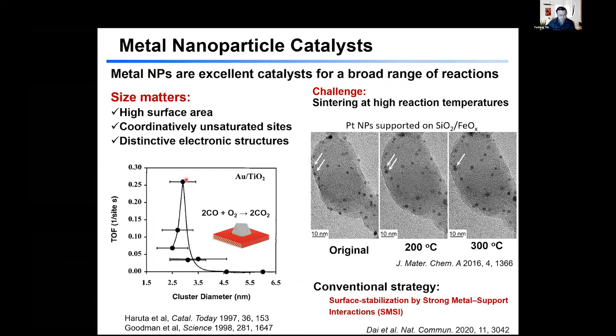I also used this same example, gold nanoparticles on titania for CO oxidation. But I use this reaction to talk about the importance of size. Apparently there's a magic size that works the best, and slightly larger than that, if you go to 4 nanometers, the activity disappears right away. So very small particles are very important. They have high surface area, and they also provide abundant coordinatively unsaturated sites, and opportunities for distinctive electronic structures. That's why they are very active, and they can also be very selective.